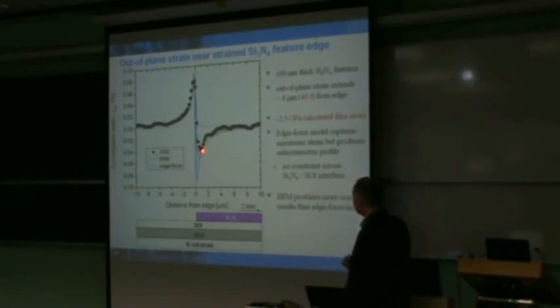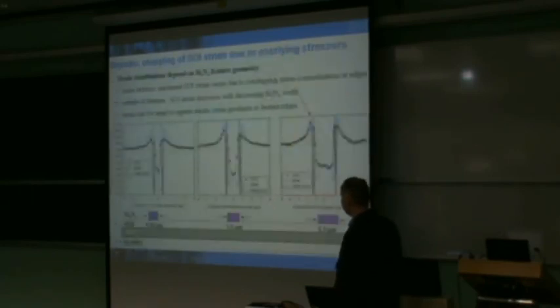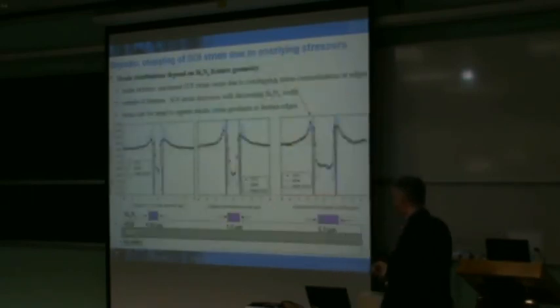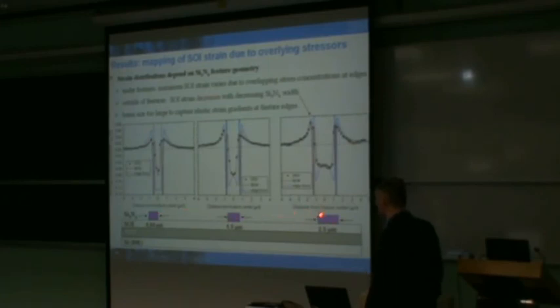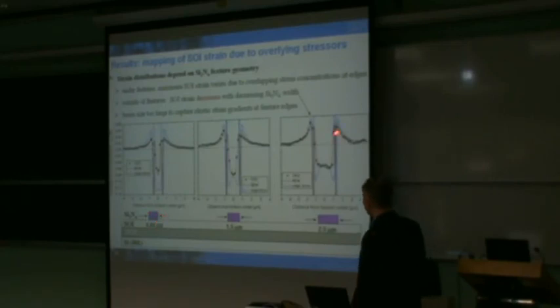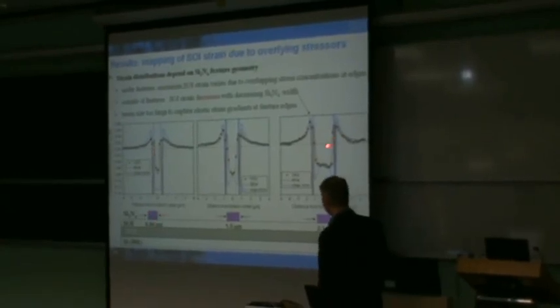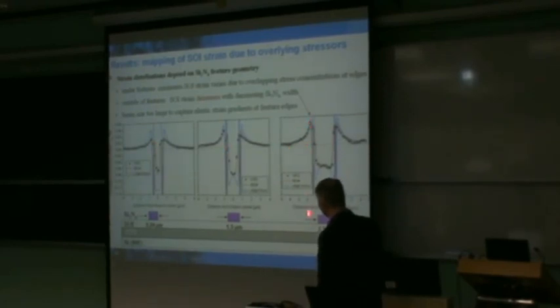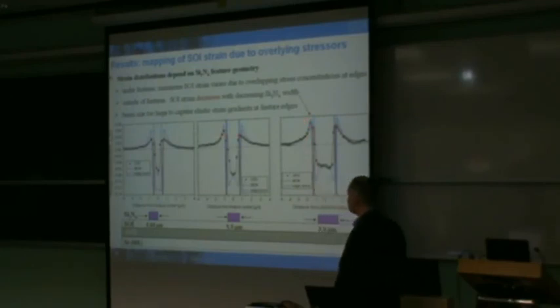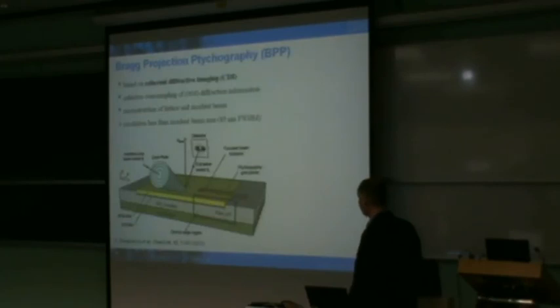In this case, I'm showing the results of the boundary element method, as well as the anisotropic edge force. You can get something that corresponds to what we see. And then just briefly, let me go through one of the key aspects here: these are overlying stressor structures. As device dimensions are decreasing, the stressor volumes are decreasing, and so we're actually marching to the left. Therefore, the amount of elastic strain that we're generating in the regions of interest, which correspond to these regions here, is also decreasing. And so we have to look at new ways and new geometries to help facilitate stress engineering. There are other examples.